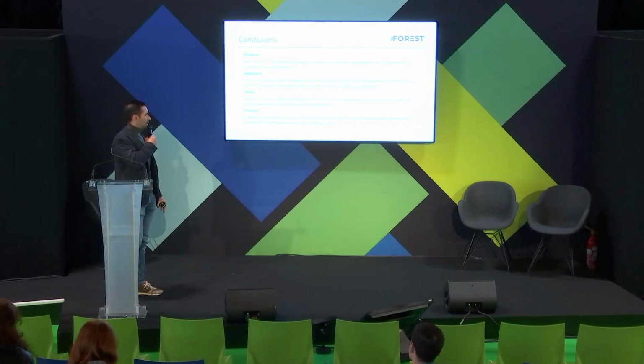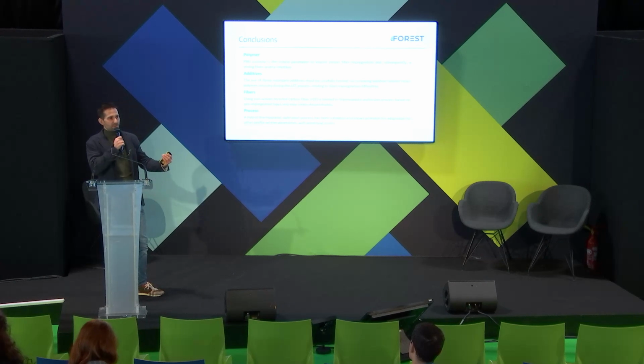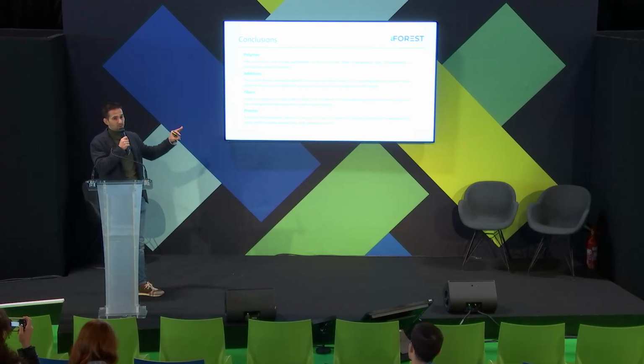Regarding the fibers, using non-woven recycled carbon fiber is limited in thermoplastic pultrusion, and I tell you why. The non-woven doesn't have a preferential direction, so when you stick it in a mold with high pressure and temperature, if there is not a proper flow inside, the non-woven doesn't want to be pulled in one direction. So what we did here is just lowering the ratio of non-woven, adding more thermoplastic, so there is more fluid inside of the mold to make the whole system flow. So we have to limit the amount of non-woven.